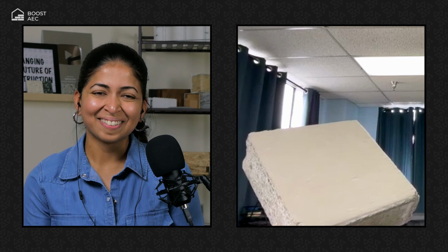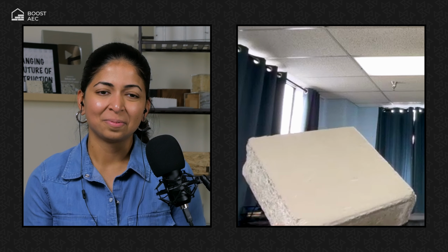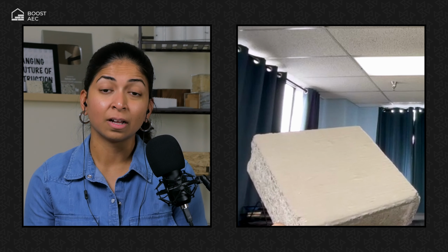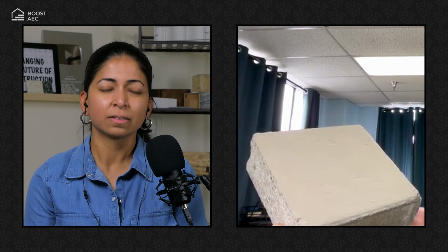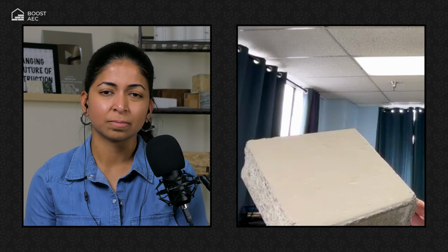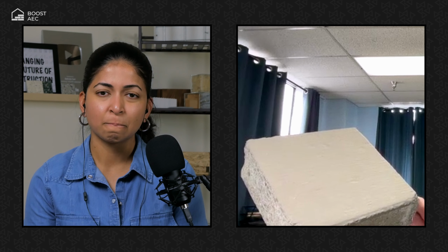So this goes on, it mixes with water. There's no VOCs. There's no organic chemistry that gets up into the air that you're breathing. And Amazon had a building full of very expensive equipment and very expensive engineers, and it was already in operation because they were behind schedule. And they just brought our material in to preserve the concrete. Now, this is an interesting sample because if you could get up close to it and see it, there's a crack right down the center, and the ceramic guard has just gone in, sealed the crack, sealed the surface, and the whole thing is completely stabilized. So when the ceramic guard goes on the surface, there's no porosity left, and the surface is completely chemically stabilized, so nothing can really harm it. Or it's very, very difficult to damage.